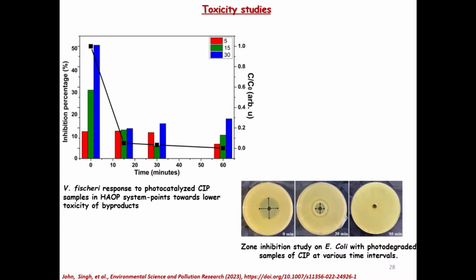So herein we have two complementary studies where we show using Vibrio fischeri as well as E. coli, using the zone of inhibition method as well as the Vibrio fischeri response to photocatalyzed CIP samples. So the sample or water had ciprofloxacin initially. It was degraded, and at regular intervals you could see how the average toxicity of the treated water decreases with time.